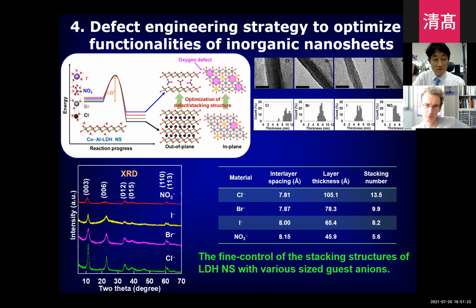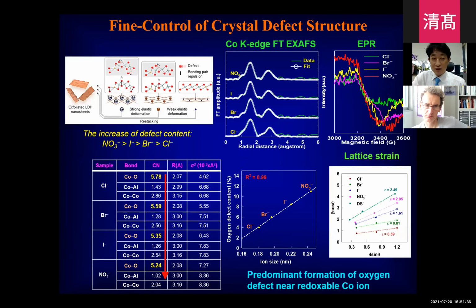As you can see here, we confirm this from the change of the XRD intensity and the cross-sectional TEM and AFM analysis. Also, we found that reassembling with larger inorganic species is effective to increase the defect level of the LDH. From the XAS and EPR analysis, we confirmed the increase of defect, anion defect. It is related to the enhancement of the elastic deformation of the LDH upon the restacking with the larger guest species, which is well correlated to the lattice strain of the LDH nanosheet.